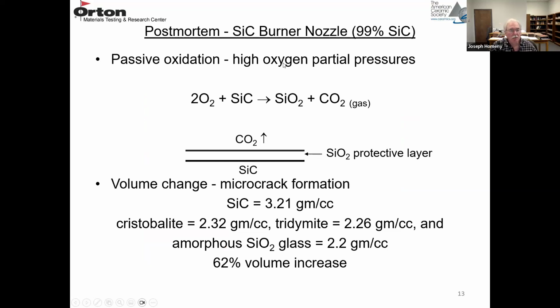And we talked about two types of oxidation mechanisms for silicon carbide, passive oxidation and active oxidation. Well, this is passive oxidation. That's where we have high oxygen partial pressures. So what's going on here is the oxygen reacts with the silicon carbide, forms SiO2, and CO2 gas comes off. And now you're forming this protective SiO2 layer. So we have your silicon carbide, your silica layer, and then the CO2 coming off.